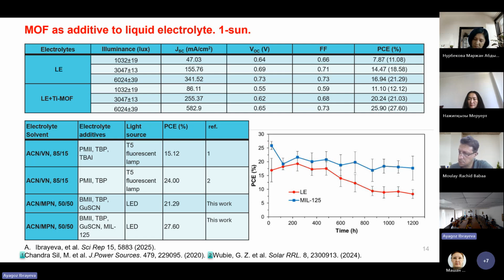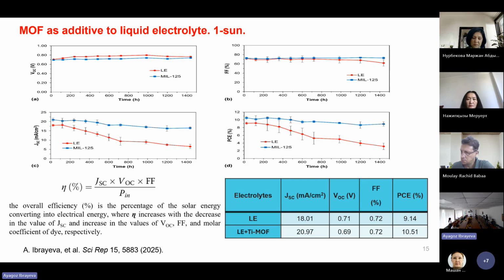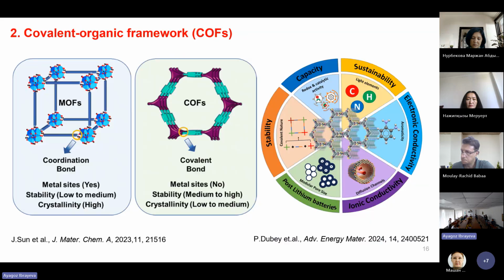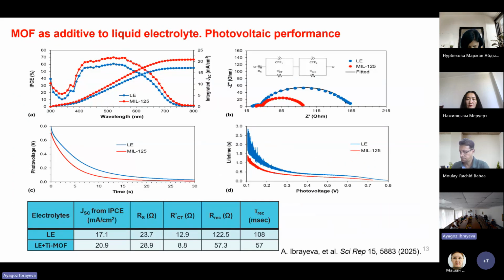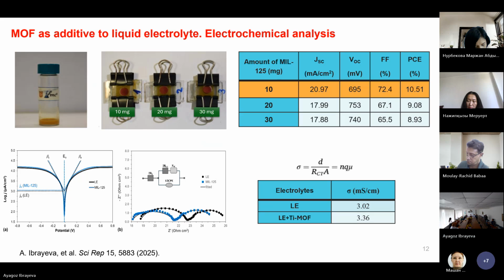My second question is about your page 13. If you use a lesser amount of MOF, your performance is higher, and if you increase the MOF, your performance decreases. Page 13, the influence of MOF concentration. You used 10, 20, and 30 milligrams per milliliter. If you increase the concentration of MOF, your performance decreases. The highest was at 10. My question: what if you used 5 instead of 10? It might increase further, or 8, for instance.